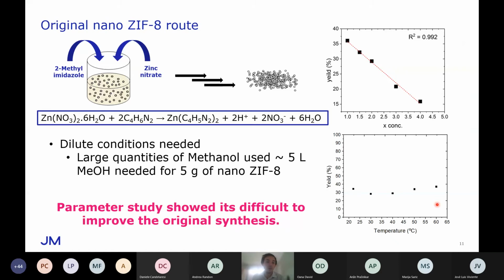If we look at the original synthesis for nano-ZIF-8, it's a fairly simple synthesis. It's made simply from a precipitation type reaction by mixing 2-methylimidazole with zinc nitrate in methanol. After 30 minutes, you get your precipitate, you filter it, wash it, and you have your material. However, to make nanomaterials, we need to use very dilute conditions. We need to use large quantities of methanol. Approximately 5 liters of methanol is needed just to produce 5 grams of nano-ZIF-8 using this method.